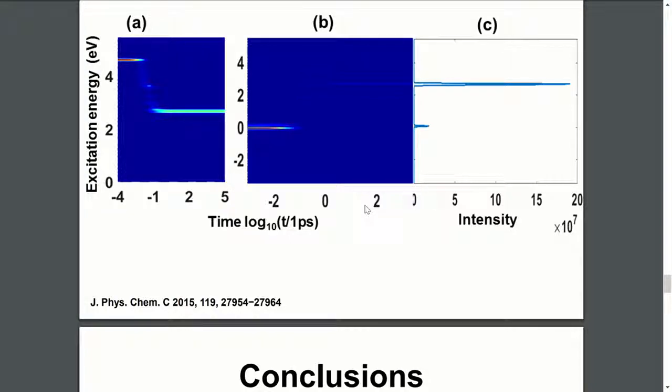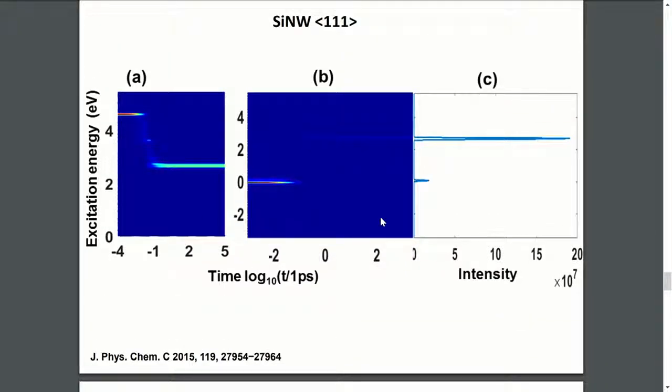You mean the paper with this calculation? Yep. For the EMA, the original, indirect. It's got about 1,000 citations from '95, so it was the very first one. And everybody since then has completely bastardized it because it didn't agree with their results. So they replaced terms in it, like with effective mass and dielectric constant, and then they basically treat those as adjustable parameters. But this one is actually the precise, exact EMA.